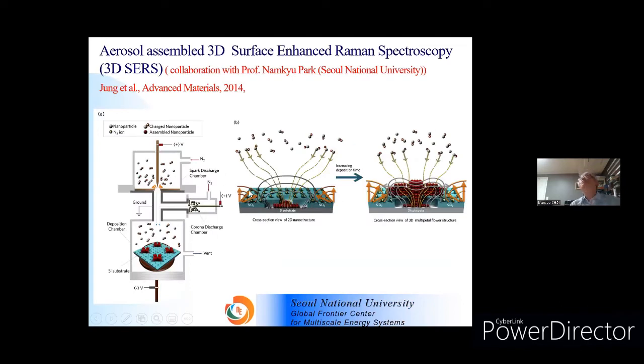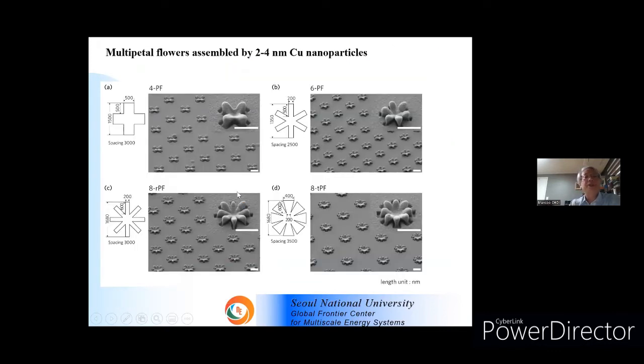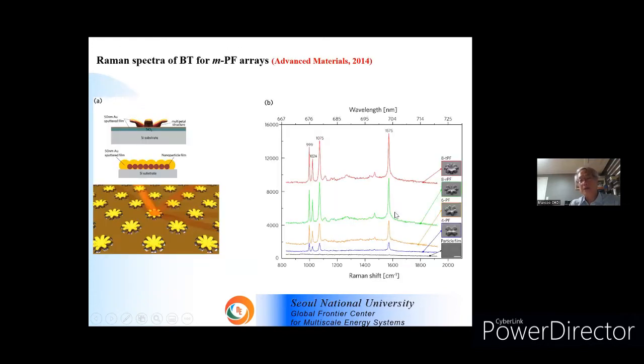We also applied our 3D structure for surface enhanced Raman spectroscopy substrate, since we can make different kinds of 3D structures: 4-petal flower structure, 6-petal flower structure, 8-petal flower structure. After depositing a gold layer, we can measure the Raman spectrum, compared to conventional particle film, shown in black.